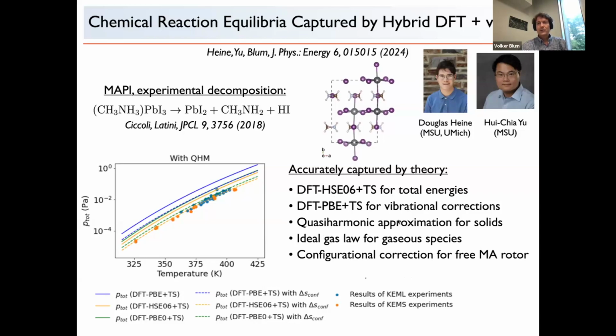We can do the quasi-harmonic approximation in this case to get volume changes in. And for the gas phase species here, we can do traditional thermochemistry and use the ideal gas law to get the temperature-pressure behavior right. And then finally, these molecules here will rotate at finite temperature. And so we need a configurational correction of the entropy for the rotor of methylammonium. But all this can be done if you put this together.